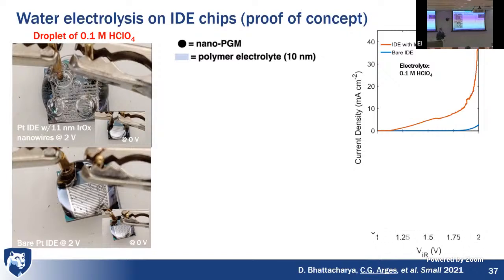You can't see the nanoscale catalyst. But with those iridium oxide nanowire catalysts, boom, a lot of hydrogen and oxygen occurring, and that's sort of what you see here in this linear sweep voltammogram.